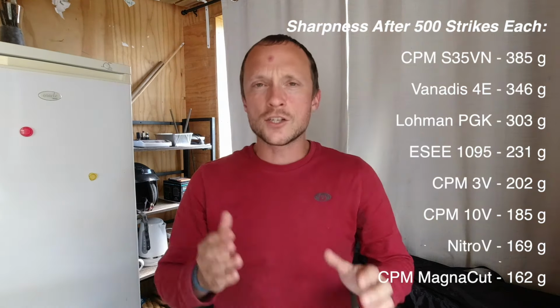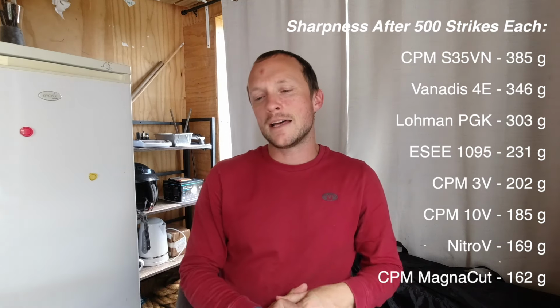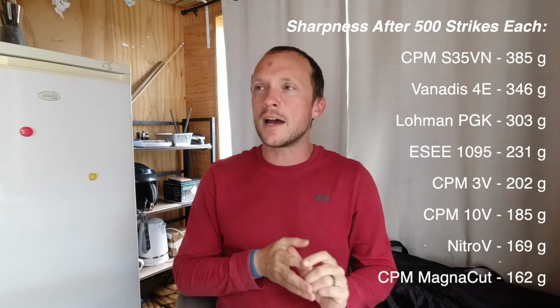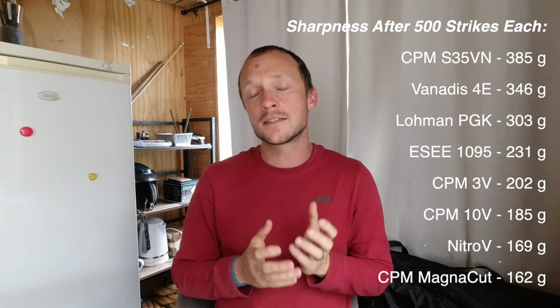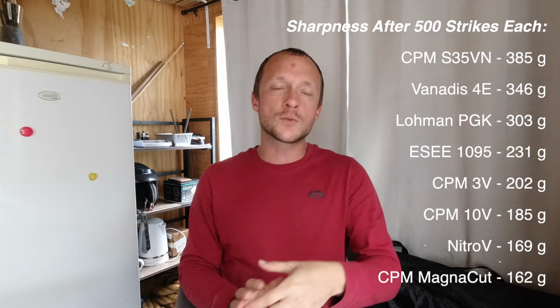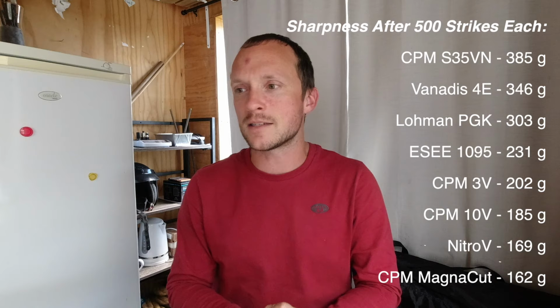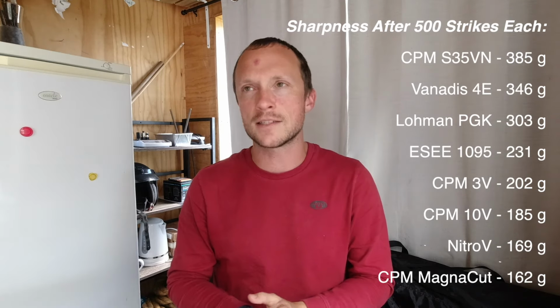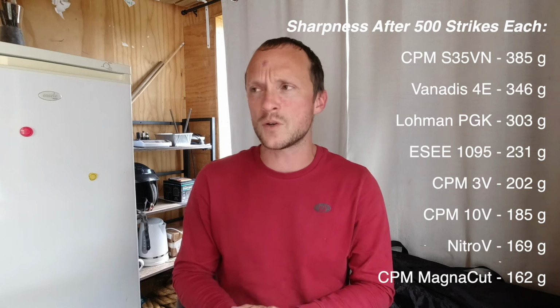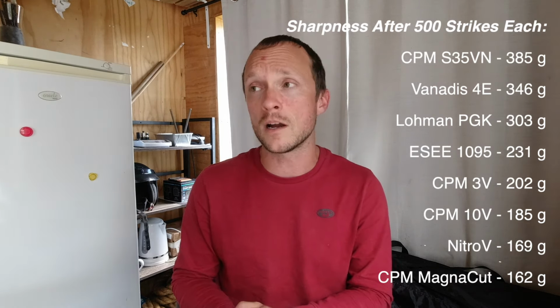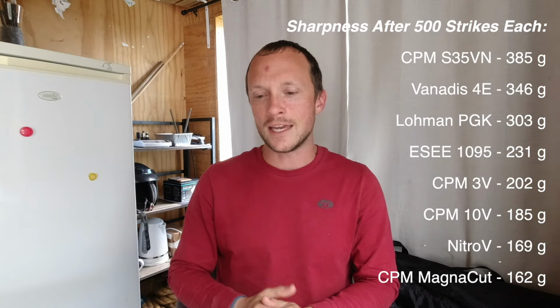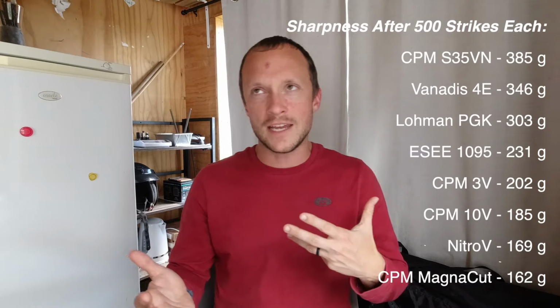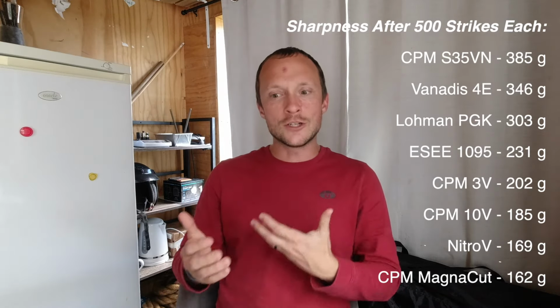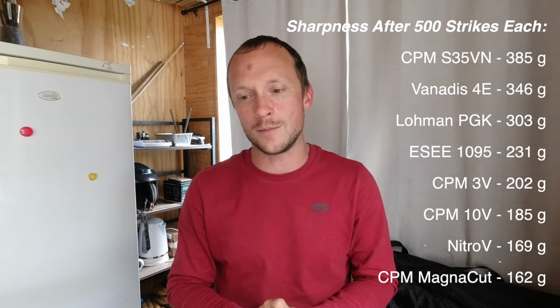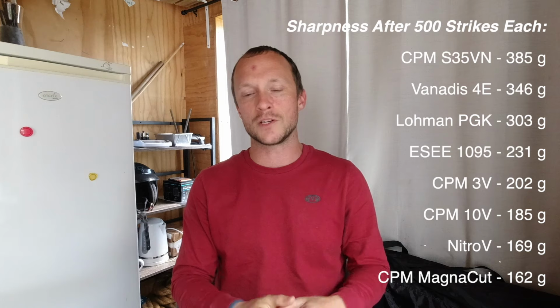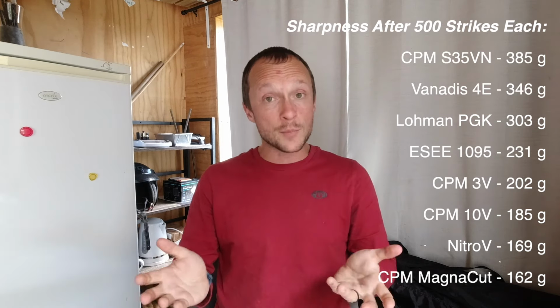Additional observations that I would form here is that the Vanadis 4 is in a Zero Tolerance knife. I have had a few Zero Tolerance knives that I had some difficulty in sharpening, and this was years and years ago, but I did find that some of them didn't seem to be at a very high level of hardness. I think ZT builds their knives to be indestructible, so it's understandable if they're rolling at a lower hardness rating, but it is interesting whether that Vanadis 4 be at 58 or 59 or 60 Rockwell, the huge difference you see between that and your 63 Rockwell MagnaCut, your 63 Rockwell Nitro V, or your 62 Rockwell 3V. It's a big performance difference there.